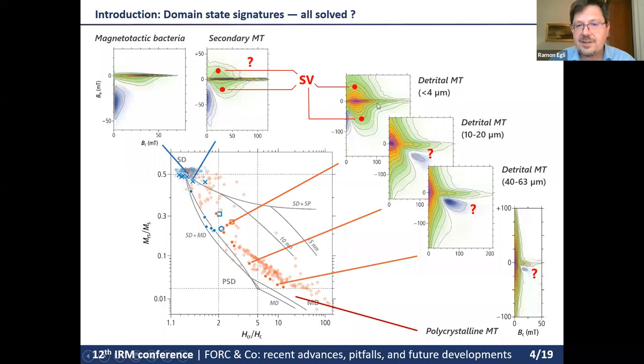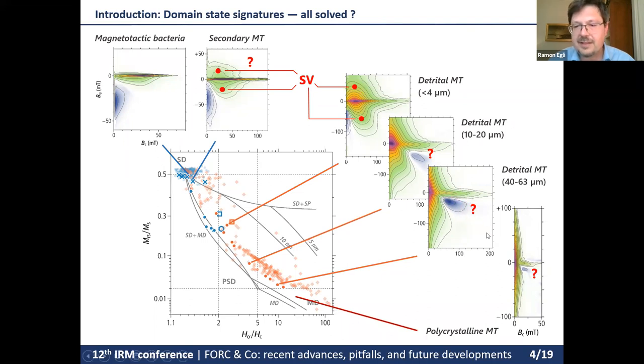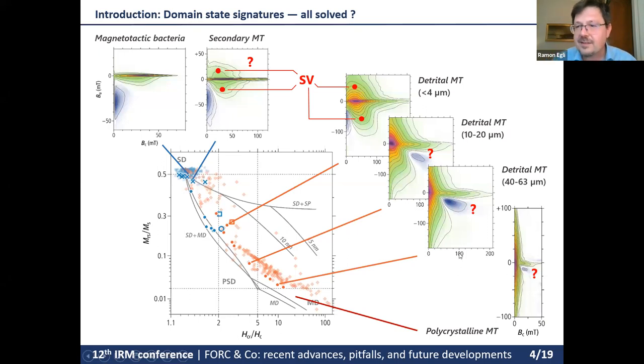Also, while the true single vortex signature does not contain negative contributions in the lower corner, when we go to larger sizes we start to see a negative contribution growing in the descending diagonal of the FORC diagram. This signature is present in larger particles all the way up to multi-domain particles. What is this signature that survives over such a large range of sizes?